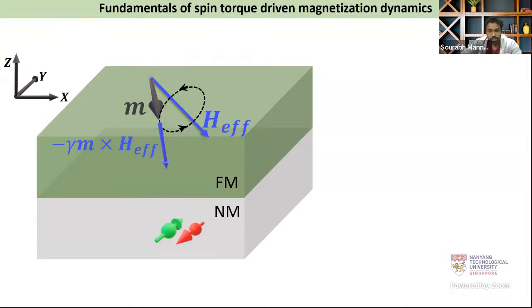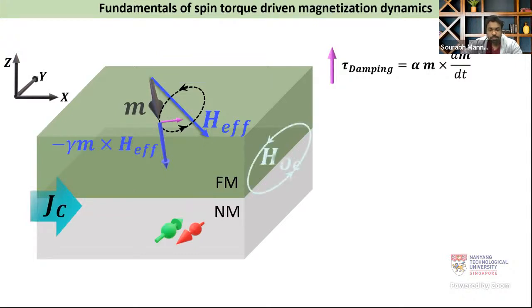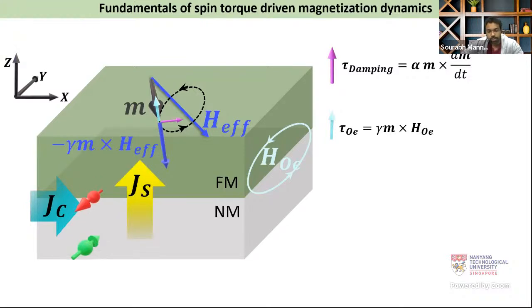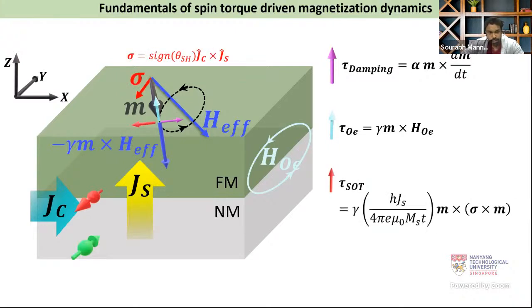Now, this effective magnetic field includes both the external field and the fields originating from internal origins inside the ferromagnet. Now, during this precession, the magnetization also experiences a damping torque, which tries to align the magnetization along the effective magnetic field. Now, if we pass a charge current through the sample, this can induce an Oersted field, which can also exert a torque on the magnetization. Now, if this bottom non-magnetic metal is a heavy metal, then due to the spin-orbit coupling, it can exhibit the spin Hall effect, where the electrons undergo a transverse motion based on their spin, and as a result, a transverse spin current is injected into the adjacent ferromagnetic material. So this spin current exerts a spin orbit torque on the magnetization, which essentially depends on the spin polarization vector denoted by sigma here.